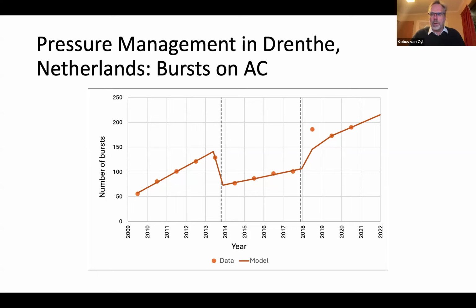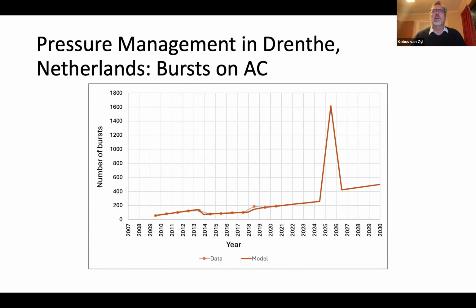So the last thing that I want to show is when the people at Drenthe then said, well, we did this experiment. We don't really need these PRVs and to maintain them anymore. What's going to happen if we just remove them and put the pressure back up to 37.5 meters? And so we put this to the model, and this is what it shows. This period up to 2019 is the historical data. And then we modeled what will happen if they increase the pressure back to 37.5 in 2025. And so you see the average failure rate is under 200 in this period. But when you put the pressure back up, it goes to 1,600 in that year.